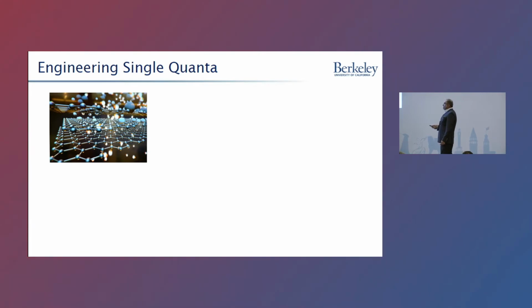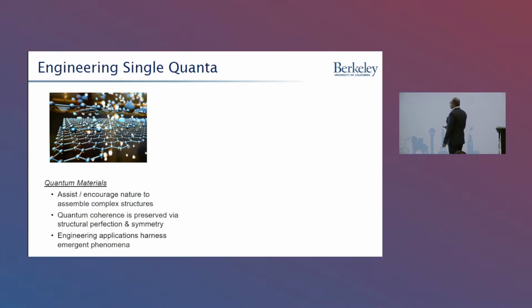This conference has also a flavor of quantum materials. So I wanted to go ahead and contrast these fields that we term in modern day as quantum materials and quantum information science. The field of quantum materials, if you like, which has two-dimensional materials or complex three-dimensional structures, looks at quantum effects where the experimentalist is assisting or encouraging nature to assemble complex structures. We have some complex synthesis mechanism to come up with, let's say, a superconductor, whether it's YBCO or an iron-based superconductor, or a van der Waals material in 2D or the like. And this quantum coherence, then, is preserved by structural perfection and symmetry. You'd like to get the best possible crystal so that you can look at this emergent phenomena, which is quantum, coming out of this.